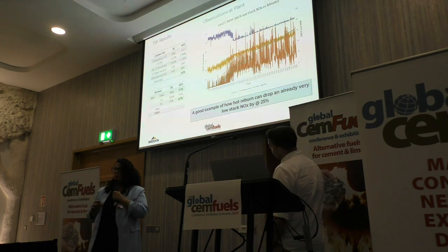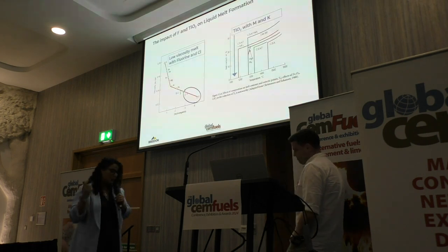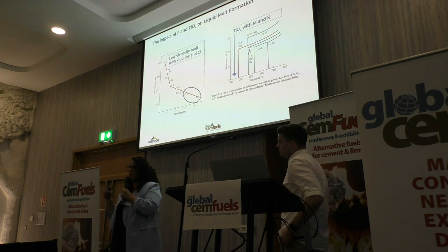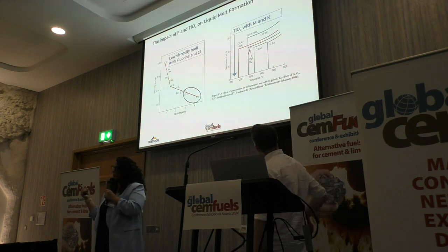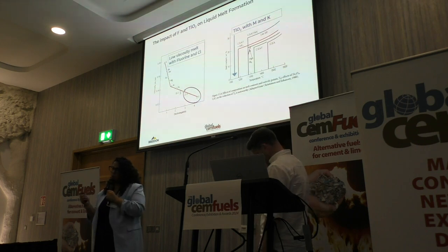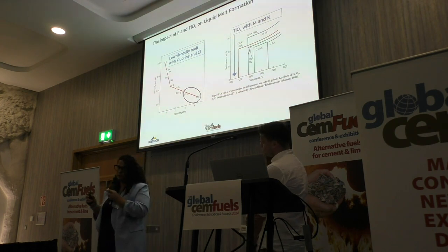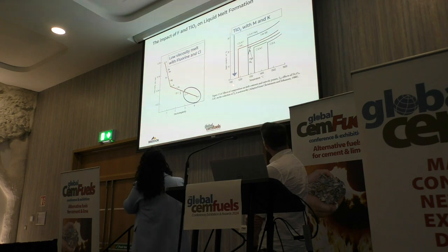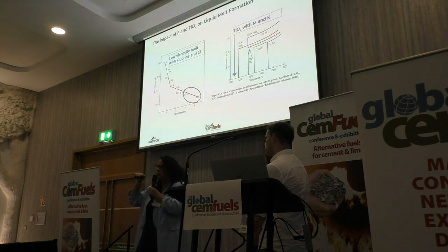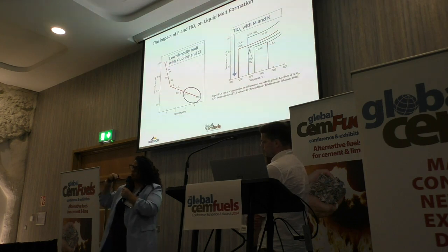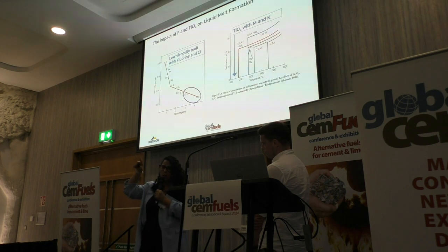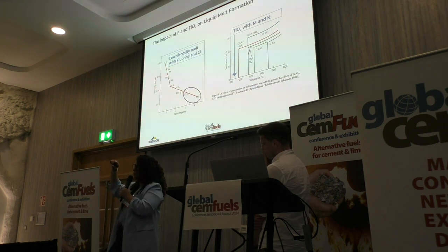Yeah, and you're probably wondering now, okay, how about the kiln balls, right? So what we also found out, completing the CFD with the AI analysis, is that the amount of the titanium that they have creates a special condition where the titanium kind of imitates the fluoride effect. So they start to have liquid phase at lower temperatures because of the amount of titanium. And with that, in the very beginning of the kiln, where you should not have liquid phase, they start to have a little bit, and the build-ups, because the SO3 cycles were going, lots of recirculations and build-ups because of the unburned fuel in the hot mill. So some slumps of these build-ups just fall in the kiln in the very beginning, and when it happens with this small quantity of liquid phase, it starts to form the ball.